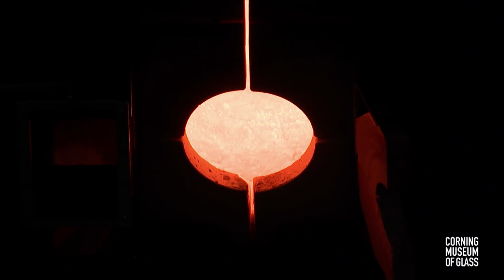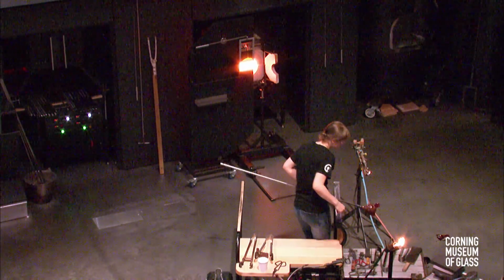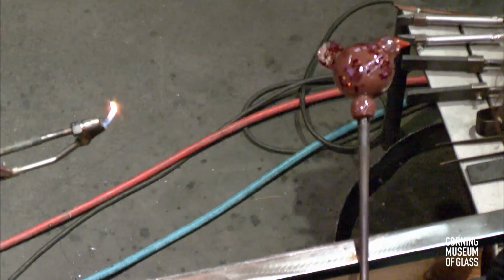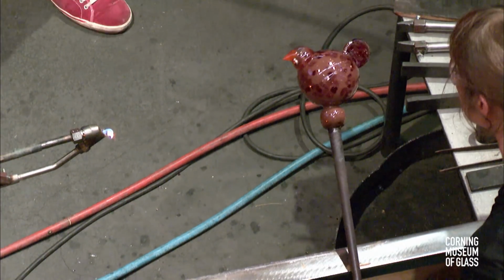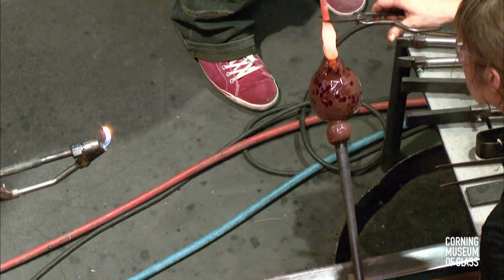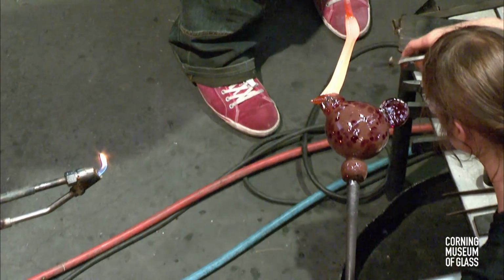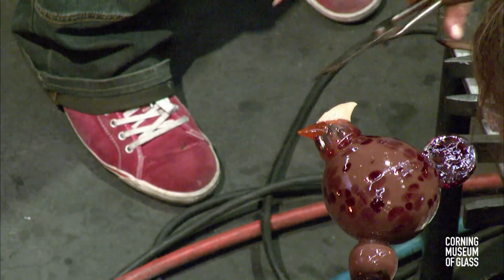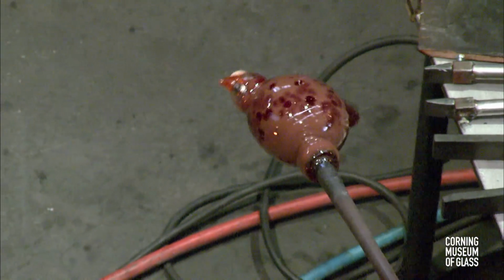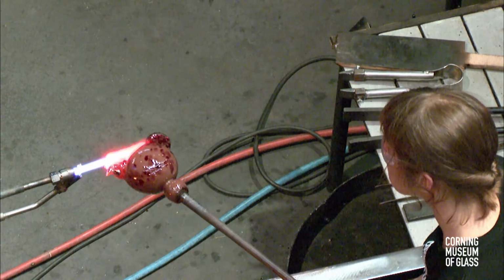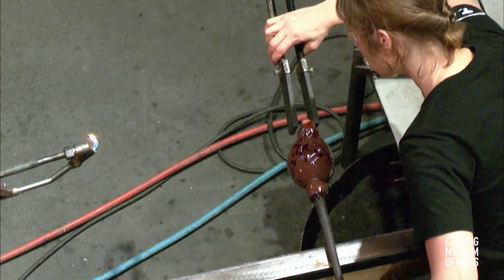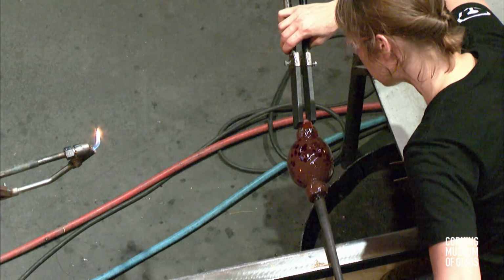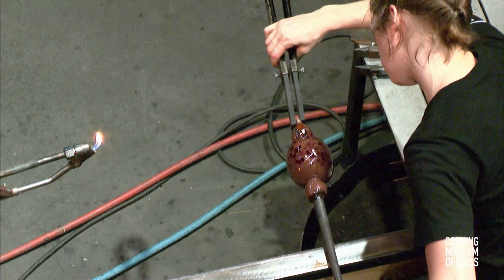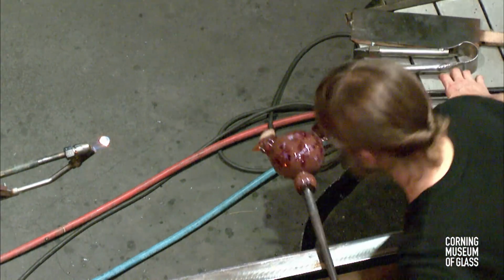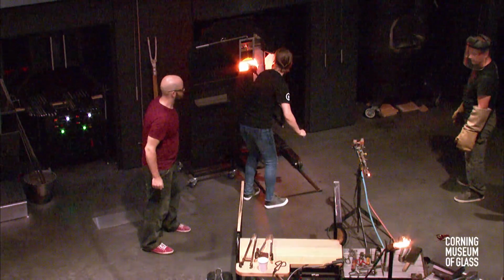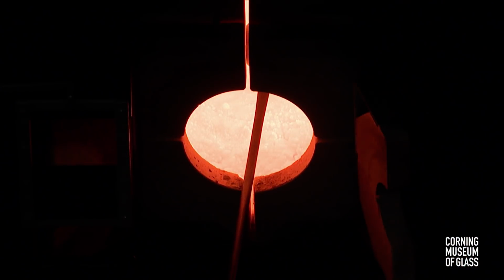So UC is putting on the safety gear over there, and that lets us know that they're almost finished with the process. Every piece of glass that we make on our stage here, and almost every piece of glass that you have ever interacted with, has gone through some sort of slow cooling process. The glass, as it cools down, shrinks, and you want it to shrink nice and evenly. If you let it sit on the table or on the floor here, this piece would cool down too quickly, it would shrink unevenly, and it would break itself apart in a matter of minutes. So for this piece and all of the pieces that we make, they have to slowly cool down overnight. That takes about 12 hours for a piece of glass like this.